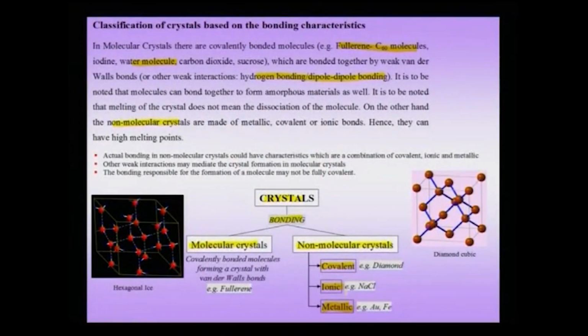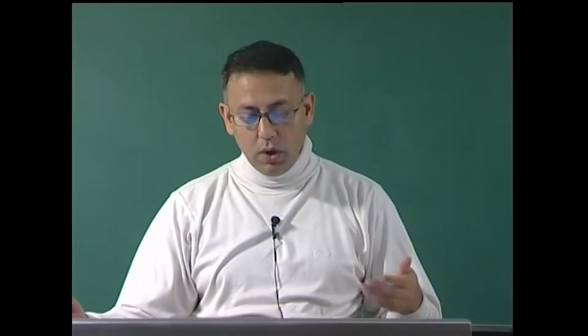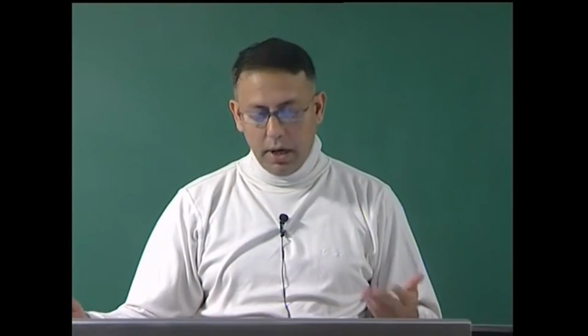Now, the bonding characteristics with respect to, for instance, the Peierls stress, which is otherwise called the inherent lattice resistance, can be compared between the covalent and the metallic crystals also. In the case of a metallic crystal, the Peierls stress is typically small, while in covalent crystals, the Peierls stress is very large, and therefore covalent crystals are not that plastic, especially at room temperature or low temperatures, which means below 0.5 of the melting point of the material. So, all these properties are naturally coming out of the bonding characteristics.